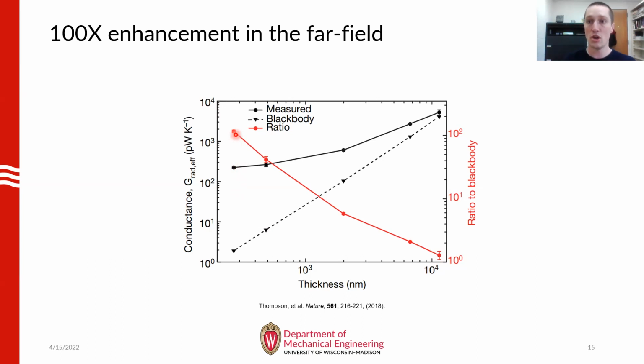Initially, this result was very surprising to me, and I was pretty skeptical because these large enhancements in heat transfer in the far field had never really been demonstrated before. That led me to perform a number of very painstaking control experiments, which you can read about in the SI of this paper if you're interested. But basically, doing those led me to the conclusion that this was not just some measurement artifact. So then the question became, can this be explained? And if so, what's the mechanism behind these enhancements?